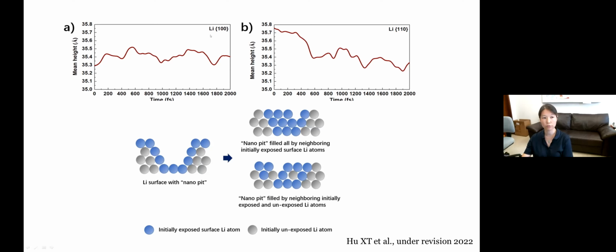And this is the result coming from the lithium 100 using the mean height, which tells you whether the pit has been filled. It remains similar. So that means the pit is there. There's not much difference in the mean height. But then in the lithium 110, you see a decrease of the mean height that's corresponding to the process that the pit has been filled.